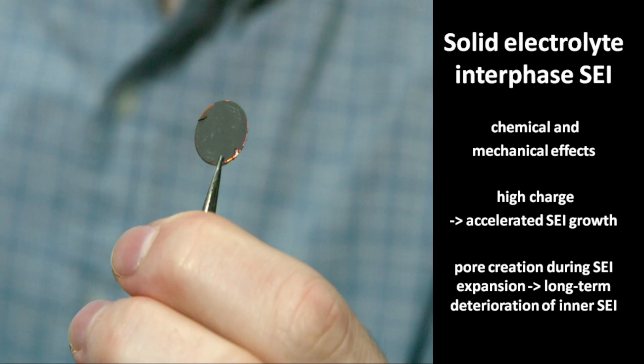The growth of the solid electrolyte interphase on the silicon surface is an interplay of chemical and mechanical effects. Due to the repeated fracture and healing, the aging behavior is complicated. At high states of charge, mechanical pore expansion accelerates solid electrolyte interphase growth. Continuous pore creation during interface expansion deteriorates the inner SEI shell in the long term.